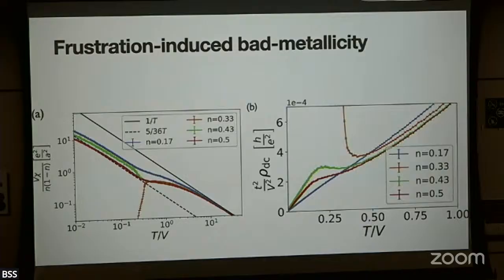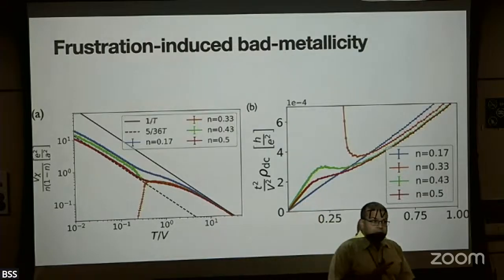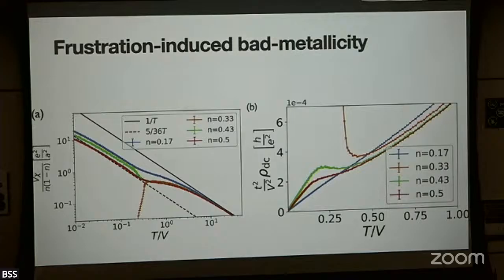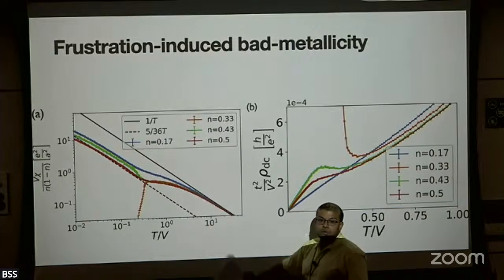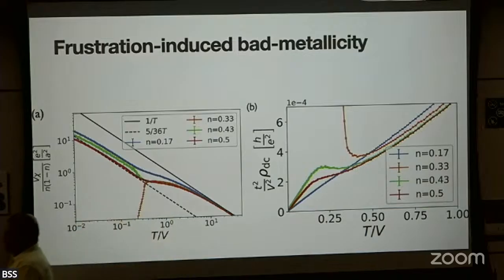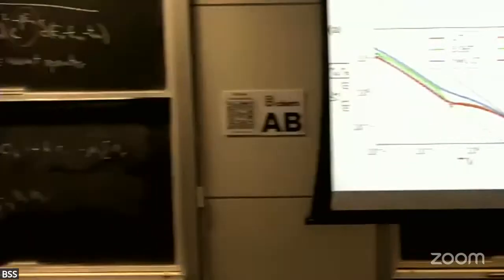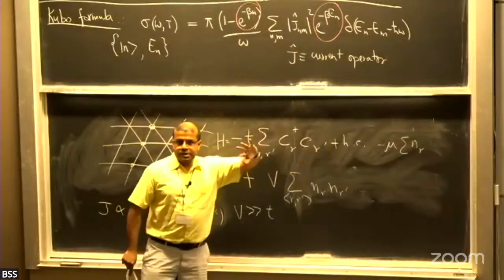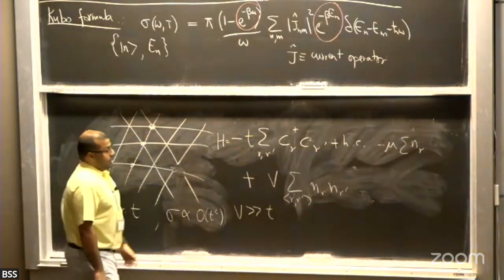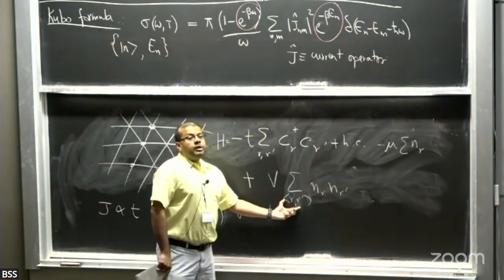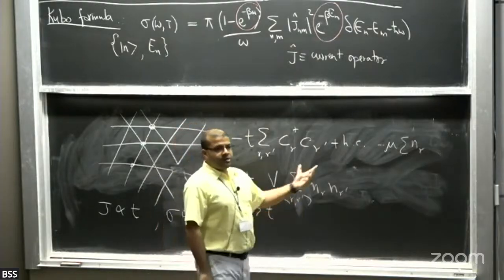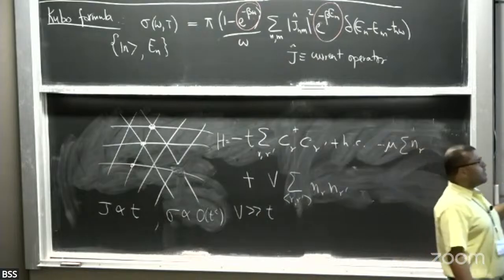And the first thing you can do is just calculate the compressibilities. And again, what this shows is there are distinct regimes, and the compressibility exhibits all kinds of non-trivial crossovers. So this is sort of a high temperature expansion with the 1/T. Now, why did we start talking about the solvable nearest neighbor model? Because in this limit where you switch off the hopping, and let's say you're at mu equal to 0, which is just the antiferromagnetic Ising model, the magnetic susceptibility of that Ising model maps to the compressibility of this model, okay? And for which there are a number of results that are known.